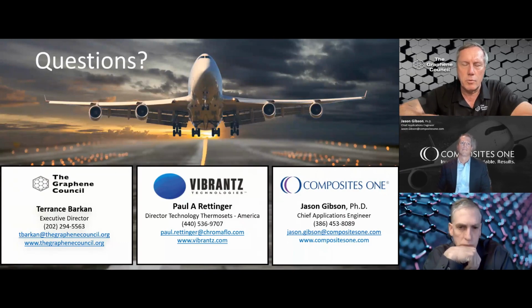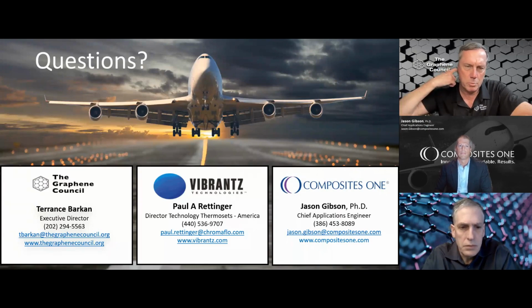This is not unusual for us to see when graphene is added for a primary purpose, and in this case, we were looking at strength properties, that it has additional beneficial properties. We actually have yet to see where graphene has been added for a primary property and it had a significant negative impact. And in this case, what Jason presented, you would expect to have embrittlement, right, by adding strength. And we had a case here where graphene added strength without significantly negatively impacting embrittlement, which is quite unusual for a material because usually you have trade-offs.